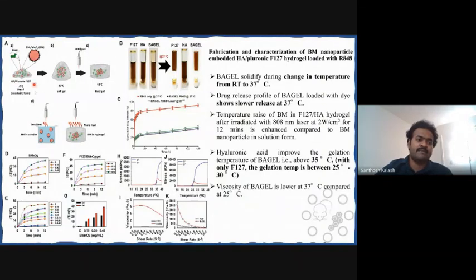So as I said before, they are liquid at 4 degrees Celsius, but when they reach body temperature, they become a soft gel. So soon after you inject it, they become like a gel, and they hold the drugs that you have injected in the tumor. And when you give a laser at 808, when the temperature reaches beyond 48 to 49 degrees Celsius, they start to become a hard gel. So the drug is retained even more, and it's not released fast.